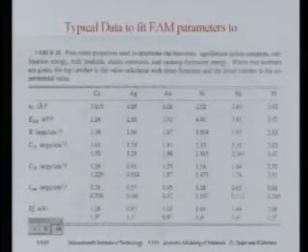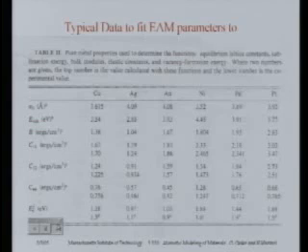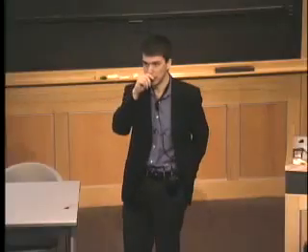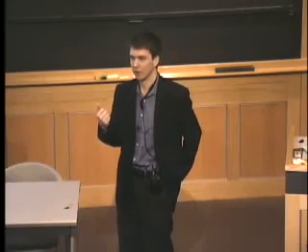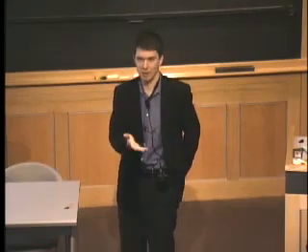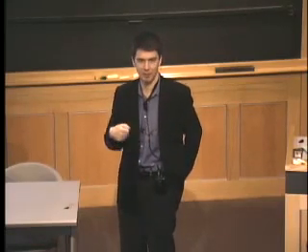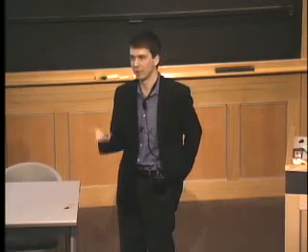Okay. What do people fit to? People fit to anything, like I told you before. The original EAM potentials were fit to a standard set of data, which was lattice parameters, sublimation energy, elastic constants, and vacancy formation energies. Now you'll regularly see papers in the literature claiming I have a better potential than you for aluminum, and I have a better potential than you for nickel, and some of that is true.